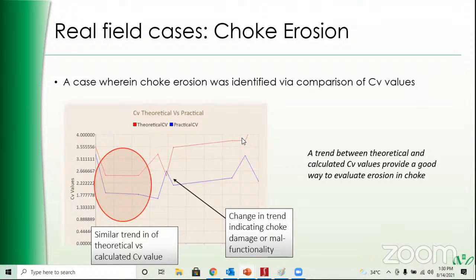and you might not be as aware of the CV values of the choke. So we plot this, and there are CV values for the choke which are manufacturer given, and then there are CV values that we calculate depending on the rate at which the well is flowing. We compare those, and if the trends are parallel to each other, the choke is performing very well. Any change in the trend indicates the choke is damaged or malfunctioning. So if you see a change in the trend, you automatically know that it's time to change your choke. This is actually a real field case.